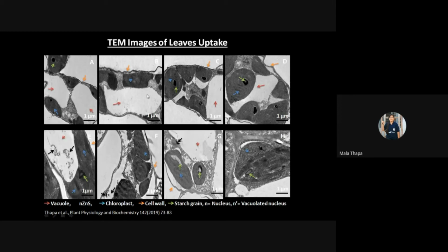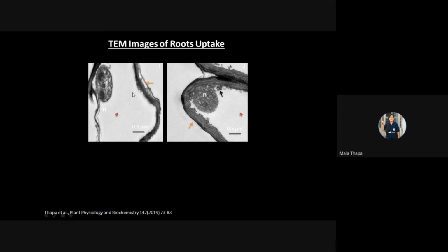These are the control leaf sections. As we can see, there are no particles present in the vacuoles of the plant leaves, whereas in the treated plant these nanoparticles are present in the vacuoles, which confirms the uptake and translocation of zinc sulfide nanoparticle from root to leaf. This is the root section of control and treated plant. Again, it confirms the translocation of zinc sulfide nanoparticle from root to leaf.